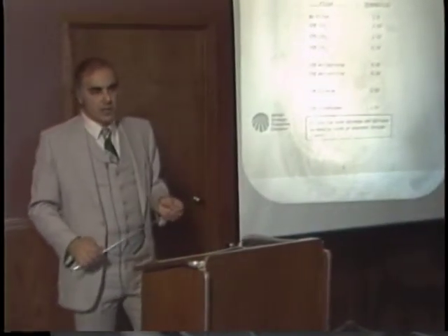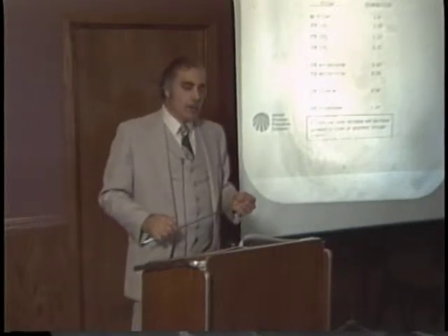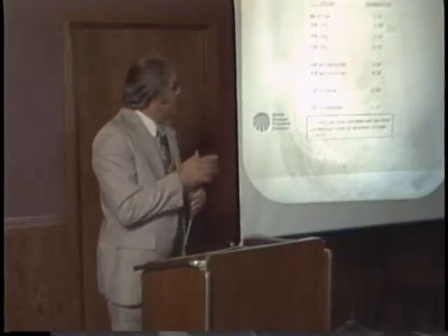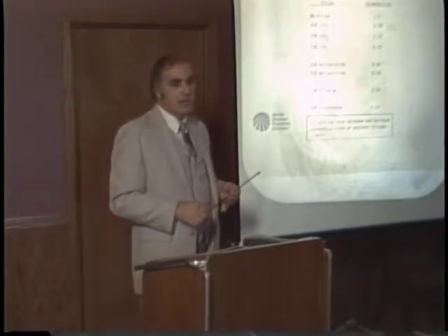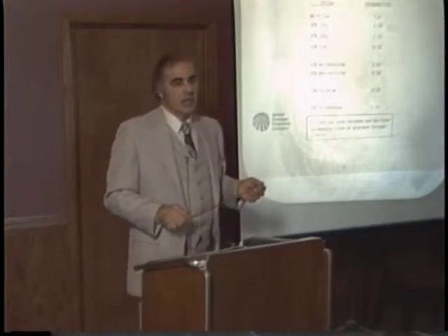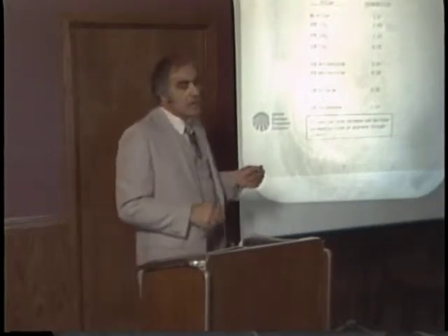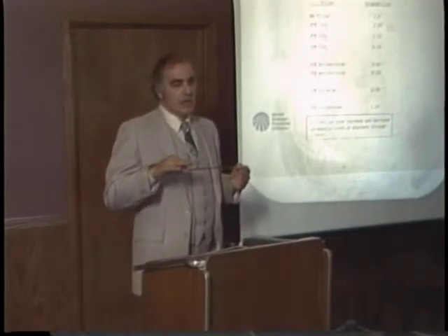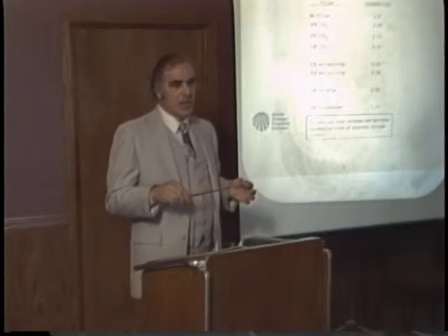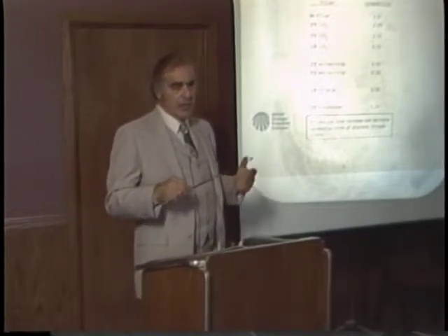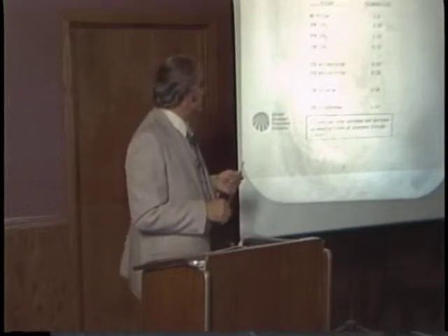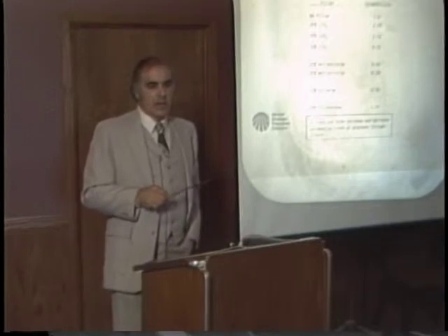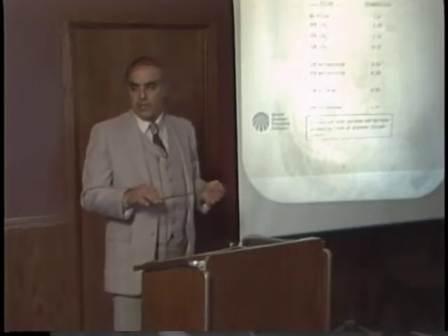We looked at the effect of several fillers on their ability to retard migration through the polymer network. The system we chose here was the B2000 system, that's the 1,2 polybutylene glycol. The reason we chose that is it's an intermediate polarity material, and it has a fairly good permeability to most things. Consequently, the effect of any filler would be enhanced in the presence of this particular matrix, and we would be able to see the effect, and it would not be overshadowed by any polymer characteristics that might retard migration.